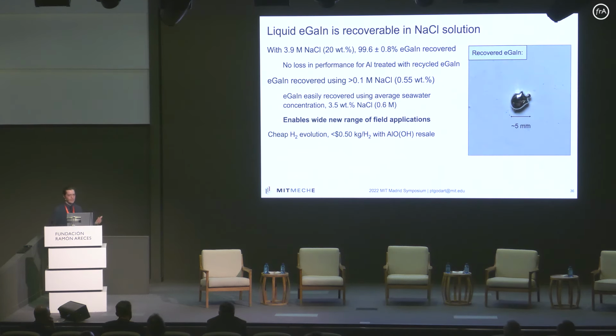And despite that, they're also much higher density than the surrounding materials, so it's very easy to separate out, and it's recoverable as a liquid, which is very important. And so in the lab, just using the sodium chloride, we were able to recover greater than 99% of the gallium and indium that we put into the system as a liquid. We recovered it back out as a very easily separable liquid. And what's very cool about this is that it also works all the way down to sodium chloride concentrations at seawater levels. So this is a process that is scalable and possible to do with just seawater.